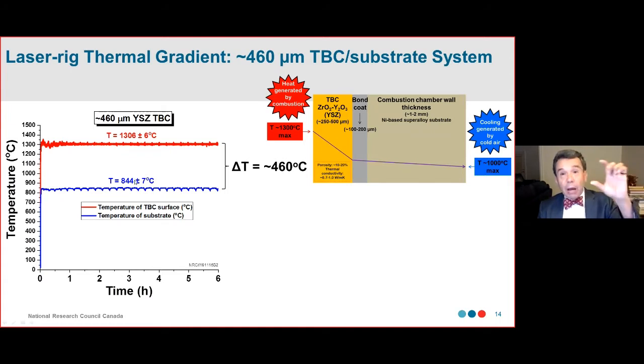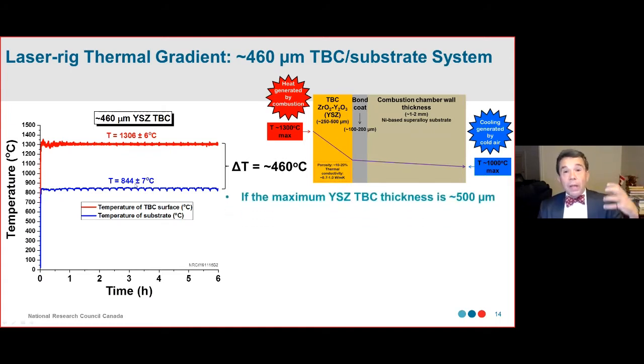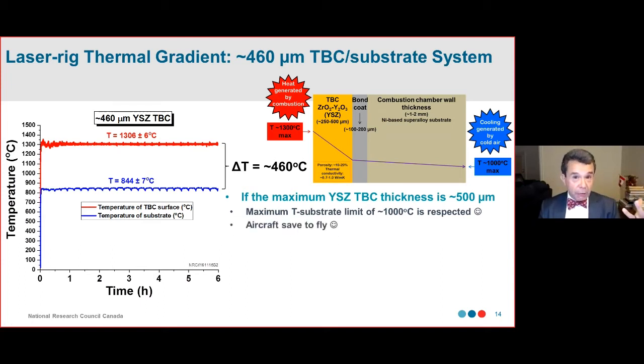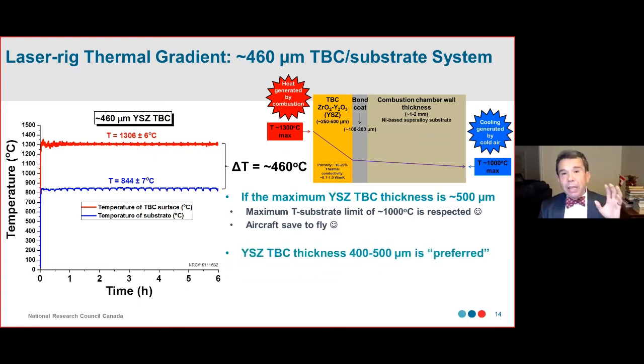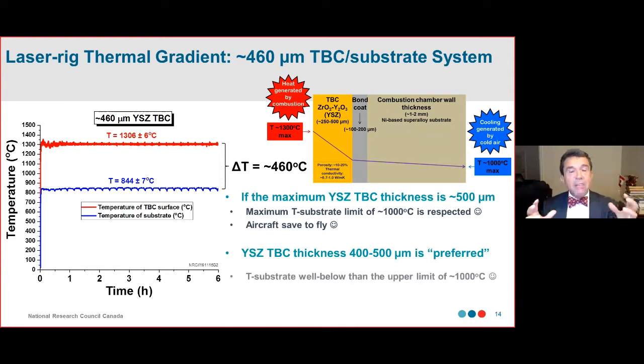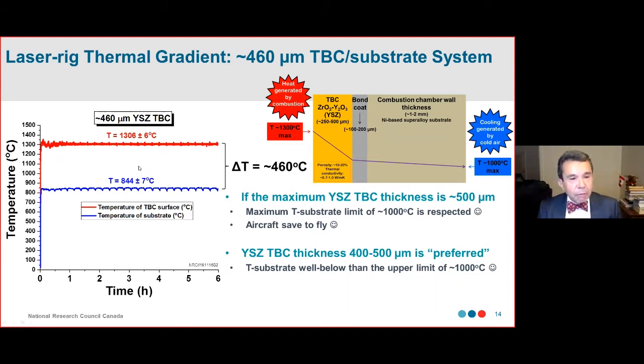So you have a much thicker coating, right? So if the maximum thickness of the TBC is about 500 microns, the maximum substrate temperature limit of 1,000 degrees Celsius is also respected. And so the aircraft is safe to fly. And of course, we can say that for these TBCs, a thickness between 400 and 500 microns is preferred, because basically we put the substrate at a very comfortable limit. We're well below the limit of 1,000 degrees Celsius. And that's why these thicknesses are preferred.